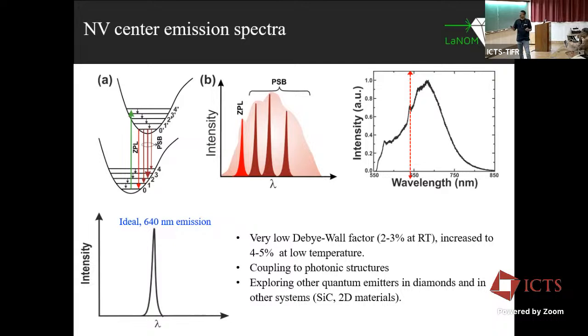If you look at the NV emission spectra, the textbook example, you have the electronic ground states and the excited states, with a lot of vibronic levels. You excite, and the population goes from 0 to 0, what we call the zero phonon line transition. It is a pure electronic state, and you also have a lot of vibronic contributions. So your NV center emission spectrum consists of a zero phonon line at 637 nanometers, and many contributions from vibronic levels.